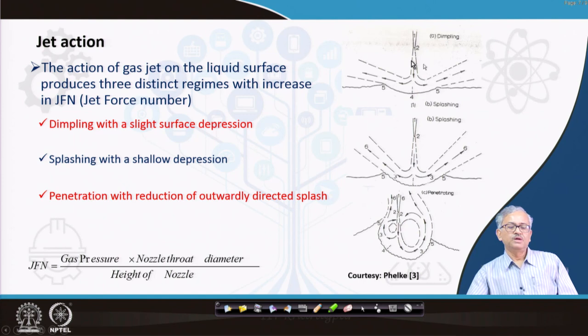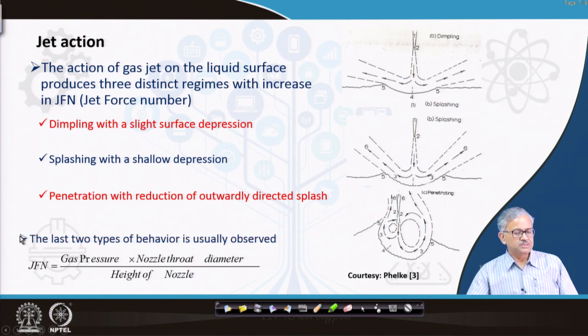So depending on the JFN you can produce penetration with reduction of outwardly directed splash, as we were discussing. In this case the splashing is reduced completely, and all the metal droplets go towards the center of the furnace, into the emulsion phase directly, rather than going towards the refractory wall. This is a very good thing, this penetration, but usually the last two types of behavior are observed. You can have this or this.